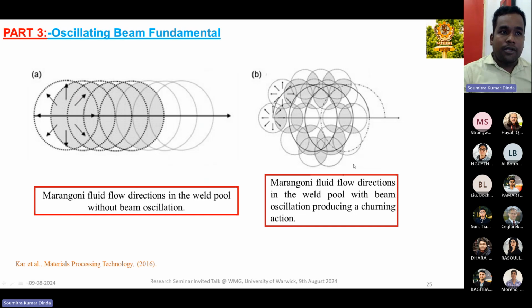But if we use an oscillating beam, this is my beam oscillation, then for the same length, our beam travels a longer distance. So individually it will form a small tiny weld pool. And now we can see that there will also be some overlapping. But when this beam moves to this side, again it will melt again. That means repeated melting will take place. So that will give you the churning action, and also repeated melting and solidification will dictate the overall cooling rate, so that our microstructure will be changed by the use of oscillating beam.